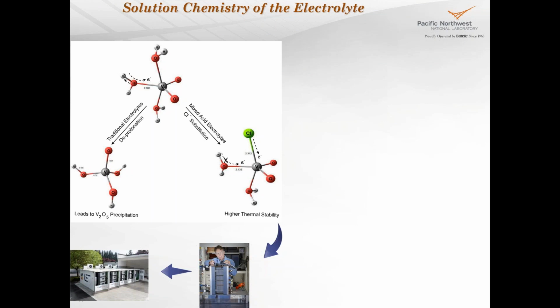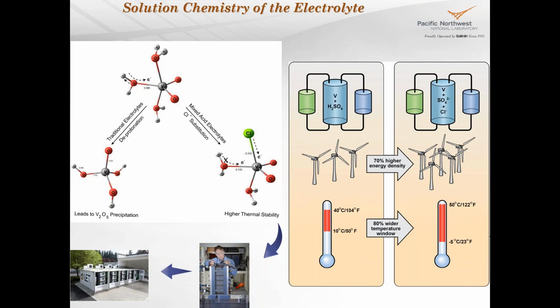The one with the green atoms, that's our new vanadium electrolyte, which is commonly called a mixed acid vanadium electrolyte. So this electrolyte has 70% higher energy density than the traditional sulfuric acid electrolyte. Also, it has an 80% wider temperature window. It is stable from minus 5 to 50 degrees C.